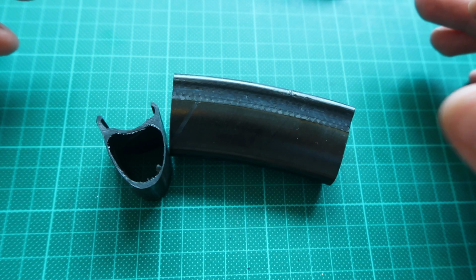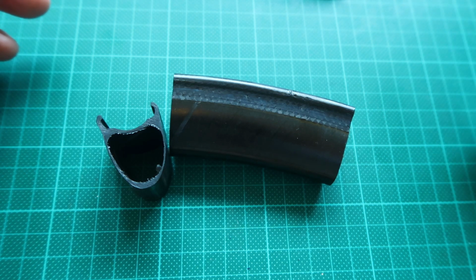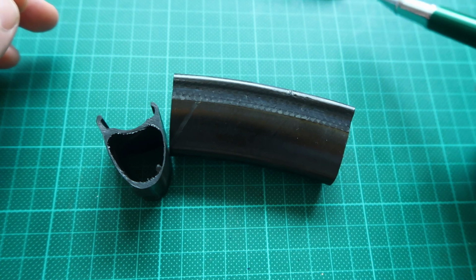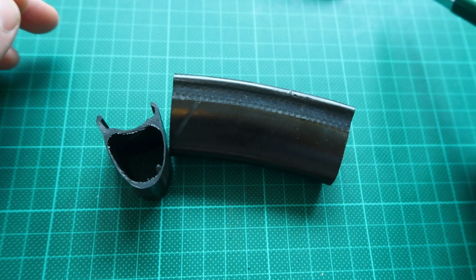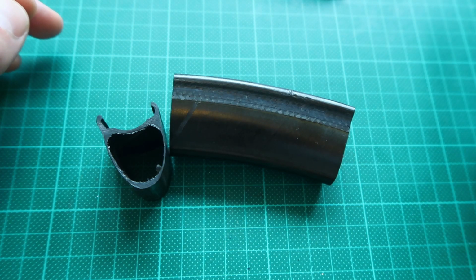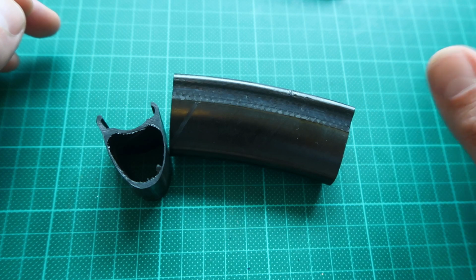Especially when you're making it out of carbon, all because of the epoxy Tg temperature, which is the glass transition temperature, where the epoxy loses its stiff glassy properties and starts going floppy. It loses a lot of stiffness very quickly above around 120 degrees. Now you can get higher quality, heat resistant resins which push the glass temperature more towards 180, which is a very expensive resin.